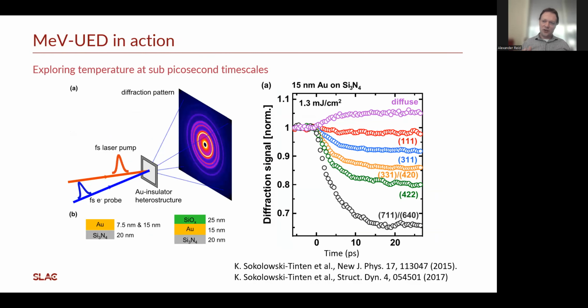Now, I just want to show you a very typical UED experiment to give you an idea of what we do before going a little bit deeper. This prototypical experiment is just looking at the thermodynamics in polycrystalline gold heterostructures. So various thin films of polycrystalline gold were made and encapsulated with either a capping layer of silicon dioxide or with no capping here.